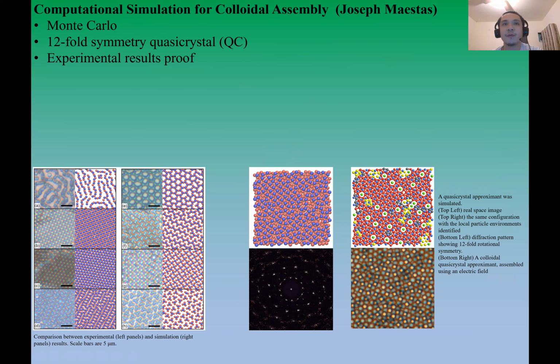Mainly, this simulation is based on the Lennard-Jones interaction and also the dipole interaction between particles. In his simulations, he controlled the particle concentration, the field strength, and also the confinement distance between the substrates. He already found that spherical particles can form different structures, as we saw in the left picture.